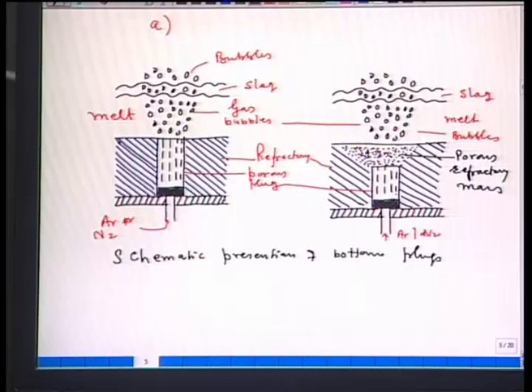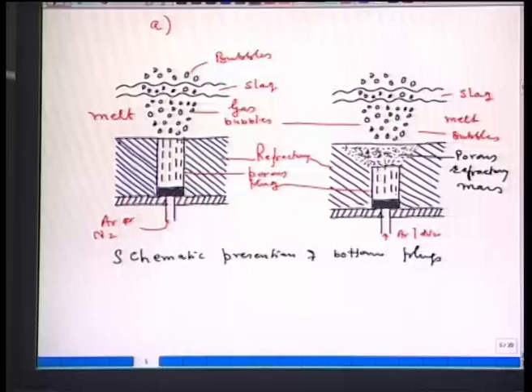So, what happens in this particular design? The porous plug does not have contact with the melt. The refractory mass of the hearth is in contact with the melt. Of course, the design of the porous refractory mass is an important feature here, because now how the gas will flow? The gas will flow through the plug, through the porous refractory, and then ultimately to the melt. So, here a larger surface area of the melt will be covered as compared to design A. If I put this as design B, here a little more area, because everywhere the gas will come, and so a little larger area will be covered by the injection of the gas as compared to that of the A design. So, this A is called direct plug, the B is called